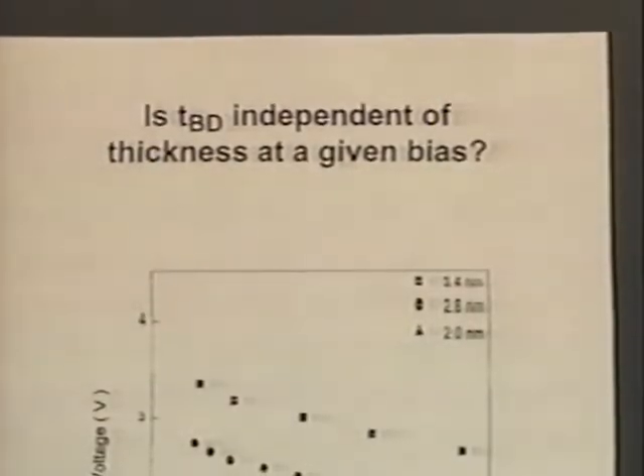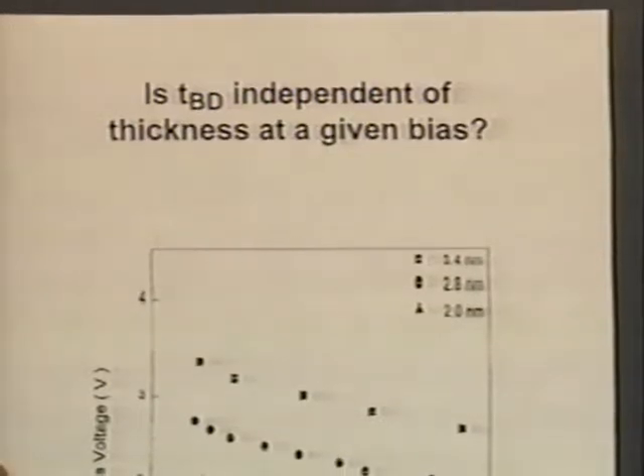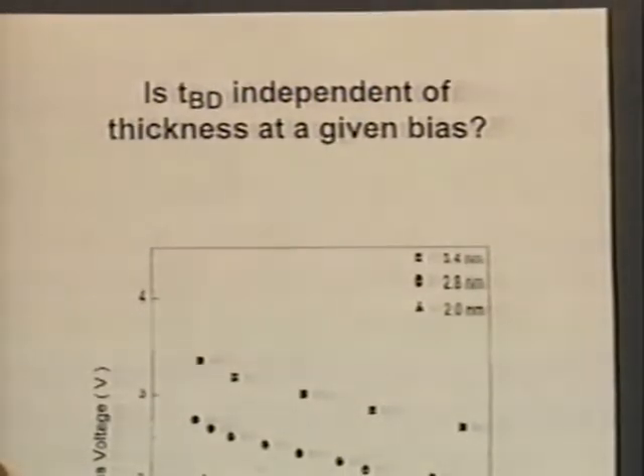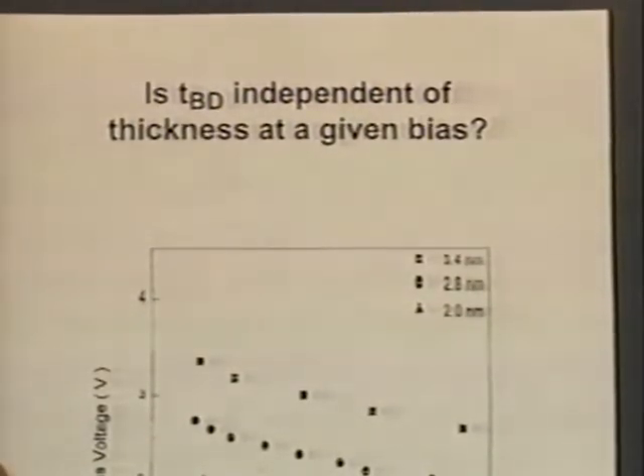What you would expect then is you sit at a certain voltage, and the time to breakdown should be constant, independent of the thickness of the device. Now, the first thing I'm going to show you is some bad news, but then I'm going to show you some good news later on. The question is: is the time to breakdown independent of the thickness at a given bias? If you sit at a certain bias, you wait a certain amount of time, then you have breakdown, then that means this positive charge is most likely related to the breakdown.